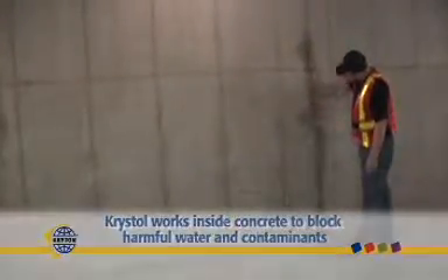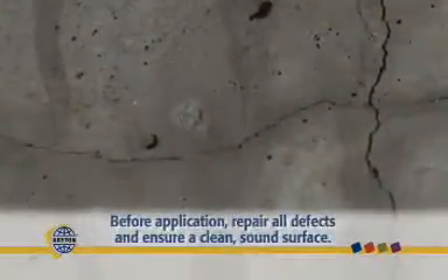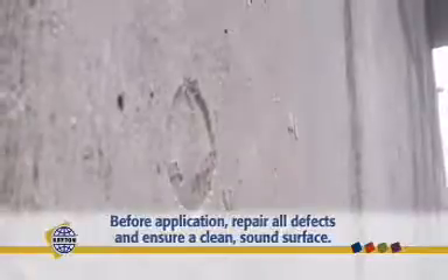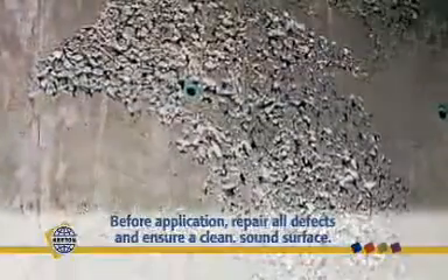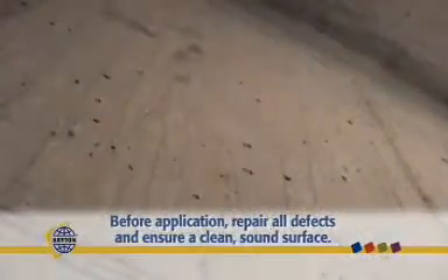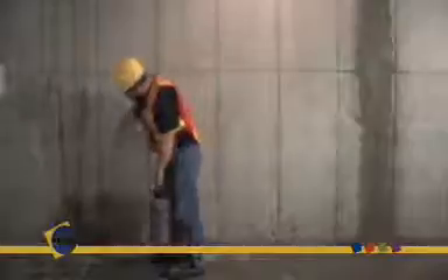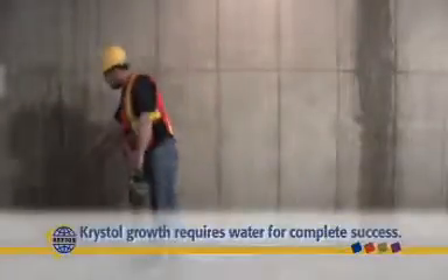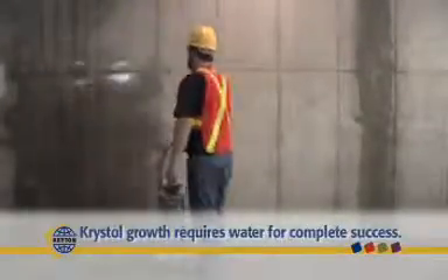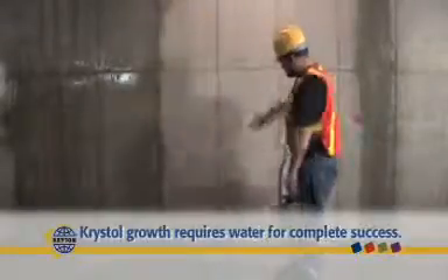Before beginning, it is important to repair all defects, including cracks greater than 0.5 millimeters in width, tie holes, pipe penetrations, and honeycombing. Ensure the substrate is clean of coatings, oils, release agents, and laitance that may hinder the growth of crystal into the concrete. Initial Krystol growth requires water for complete success, which leads us to the next very important step.